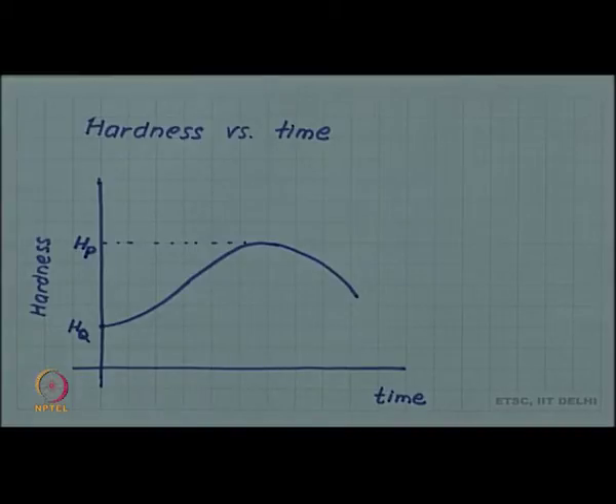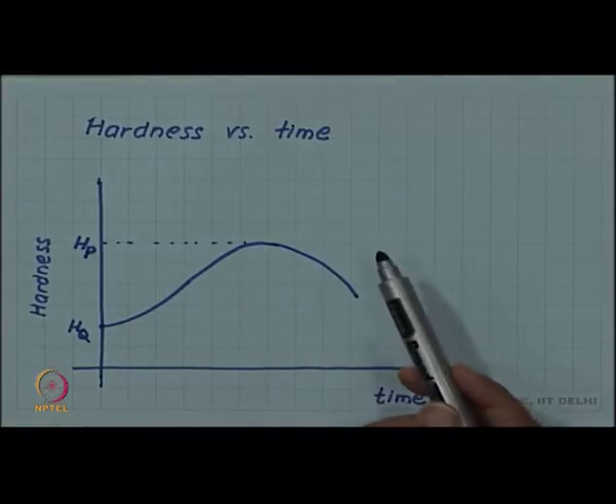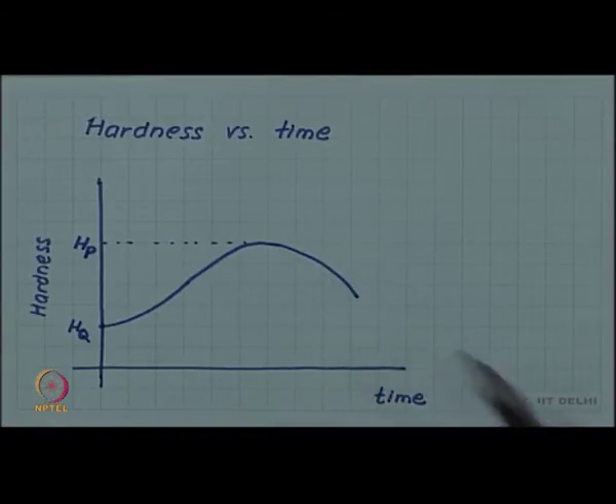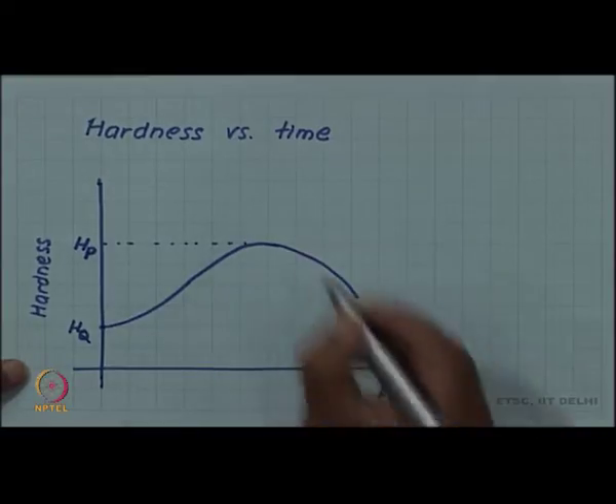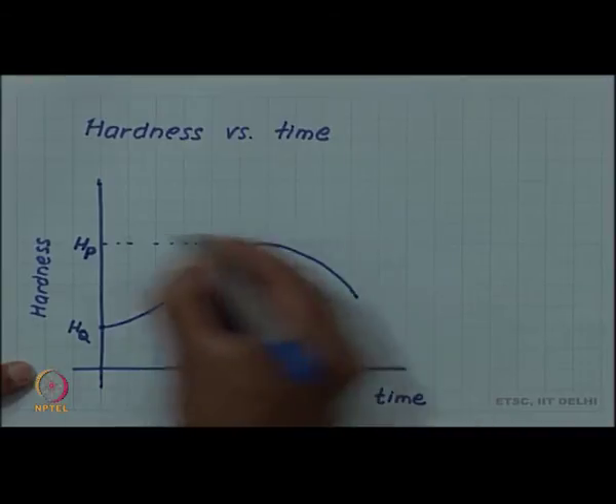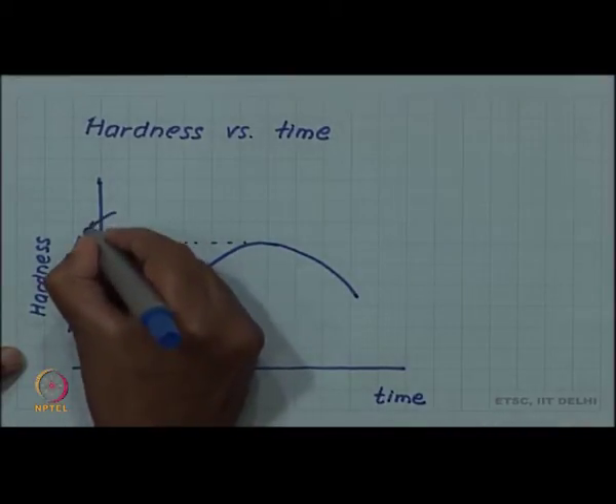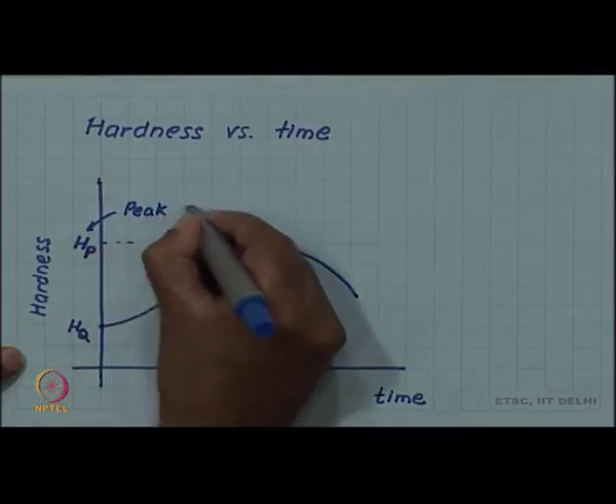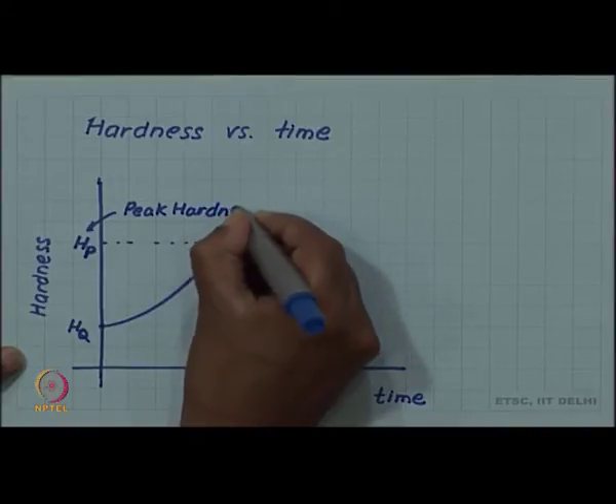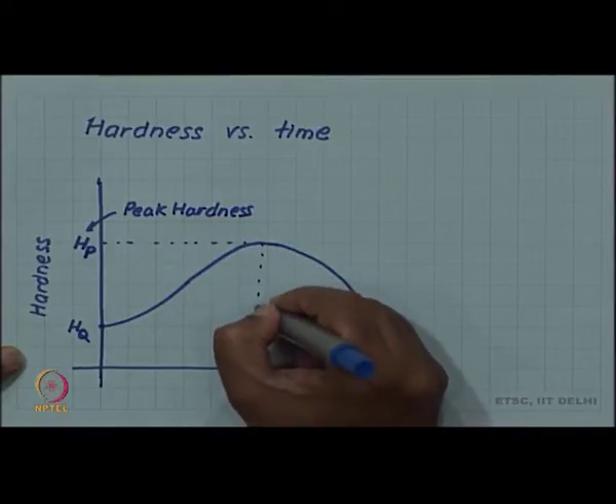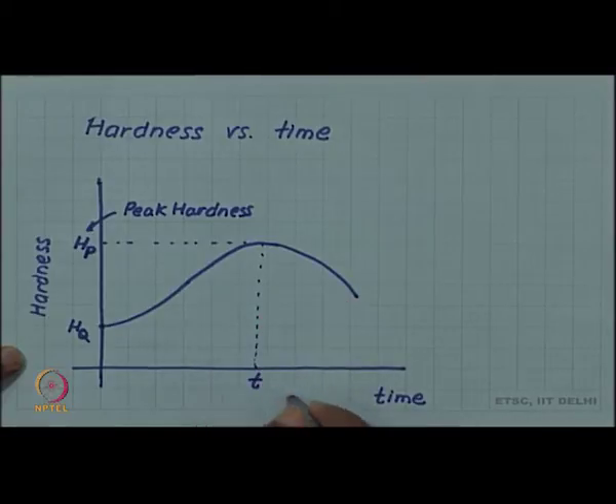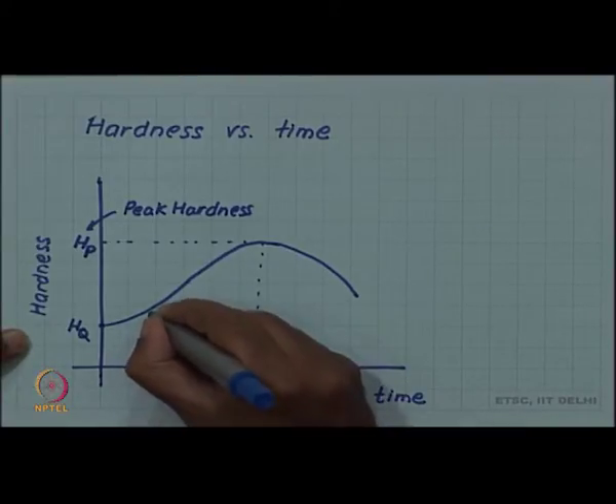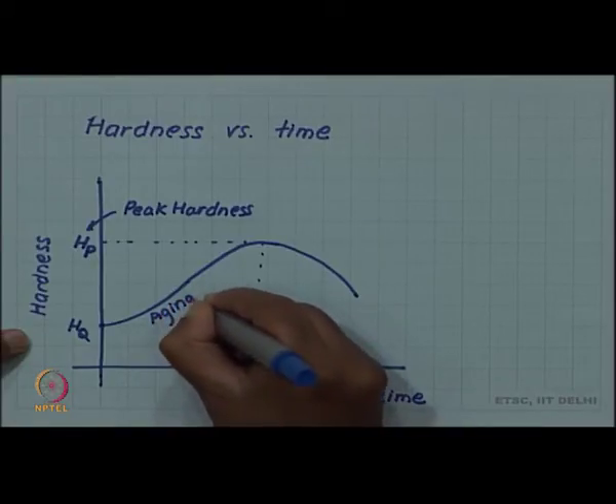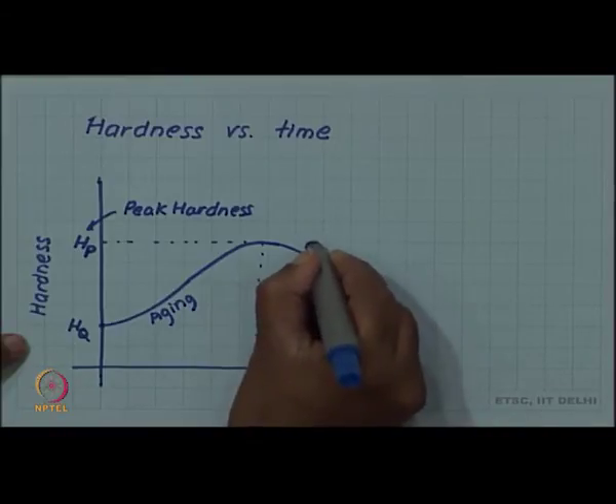So, in fact, there are two surprises: why the hardness increases as a function of time, and then why subsequently it starts decreasing. So, this point is called peak. So, HP is the peak hardness. And the time corresponding to the peak hardness, let us call that TP. So, this part of the curve is called aging, and beyond peak we call it overaging.